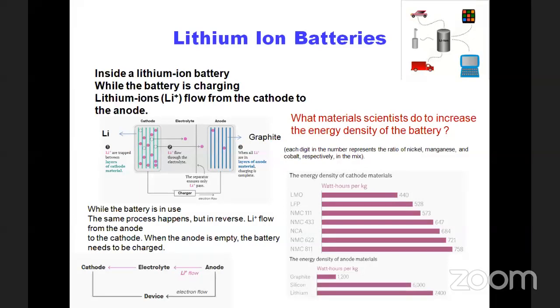But in order to increase the energy density of the batteries, people try to change the combinations with lithium. They add nickel, manganese, and cobalt, and they have achieved the highest energy density with NMC, that is lithium added with nickel, manganese, and cobalt. It has shown excellent energy density materials. Similarly, we also play with anode materials and also with cathode materials.